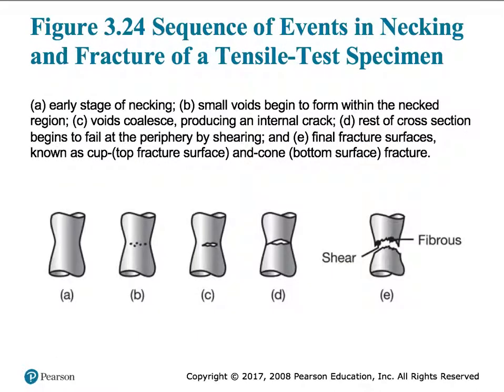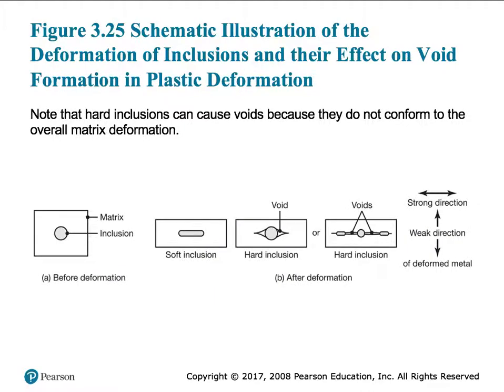Okay, so continuing further, this is if you had the material that is perfect with no inclusions or impurities. If you have impurities and inclusions, then the failure can happen in a much easier form. Those inclusions and impurities can act as the initiation points because they do not have the same properties as the original material itself, and then they can start linking up and cracking at those points. So the whole material will fail at a much lower stress than a material with no such impurities and inclusions.